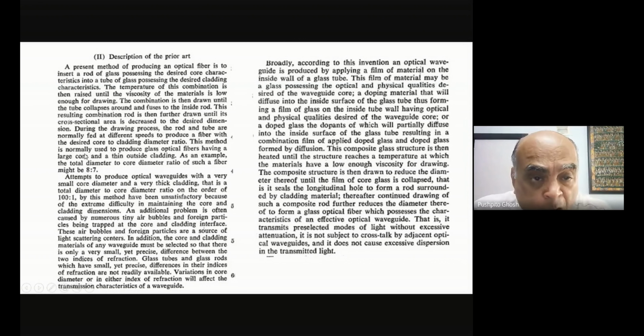This method is normally used to produce glass optical fibers having a large core and a thin outside cladding. So it is not to make the single mode kind of product. It is a relatively large core with a thin cladding. As an example, the total diameter to core diameter ratio of such a fiber might be 8:7. So it's quite different from when I've got a very thin core, and I could be talking about ratios of 100:1.